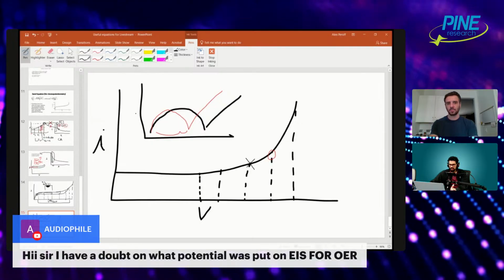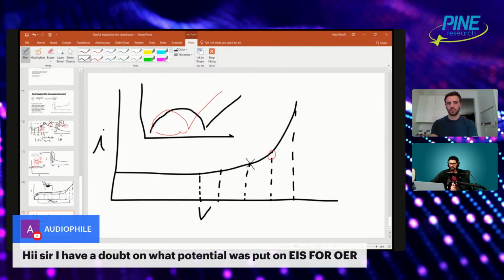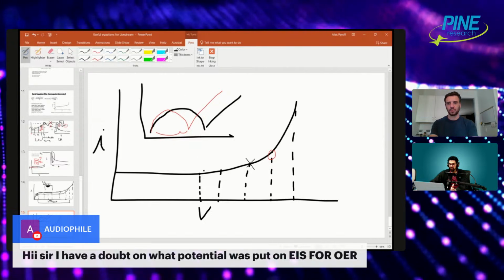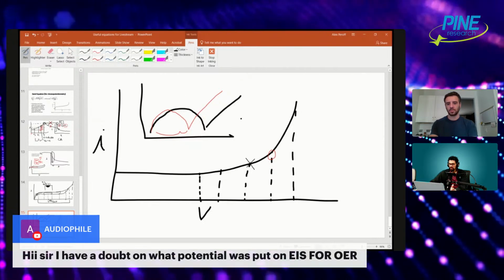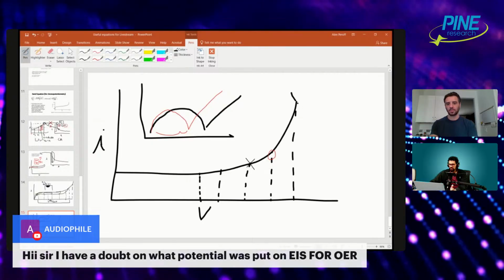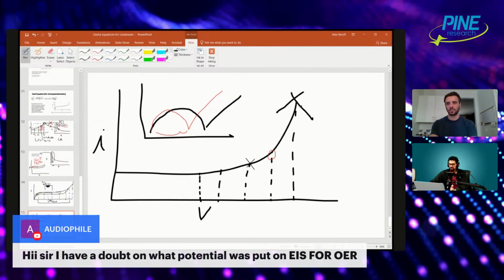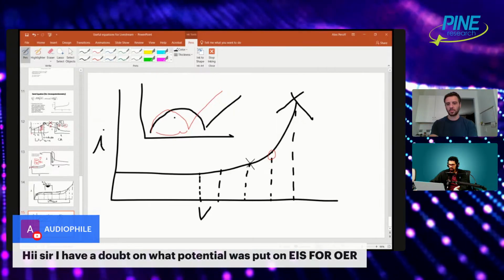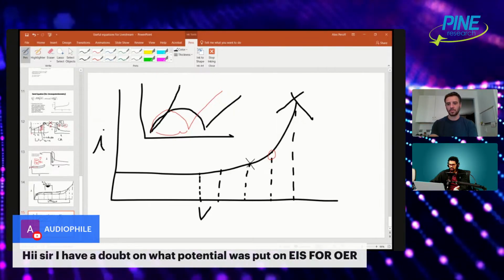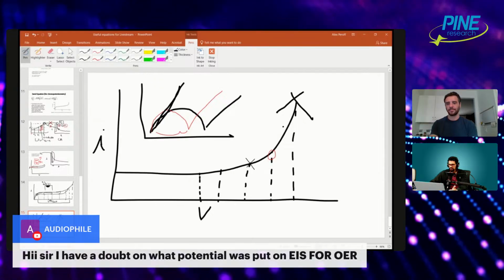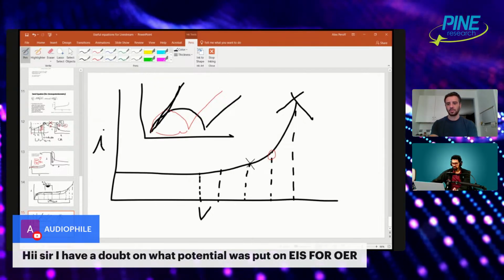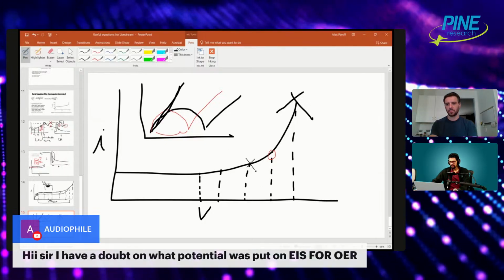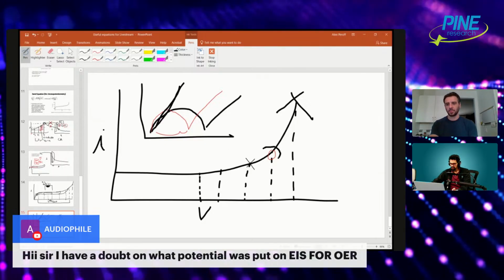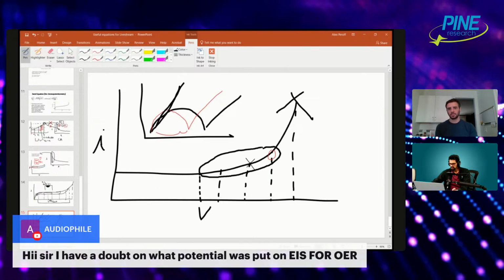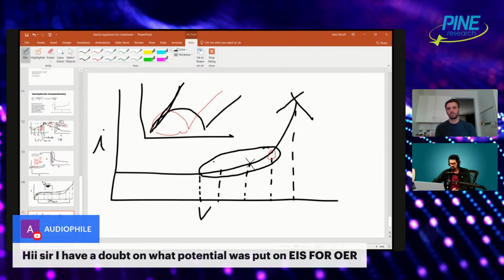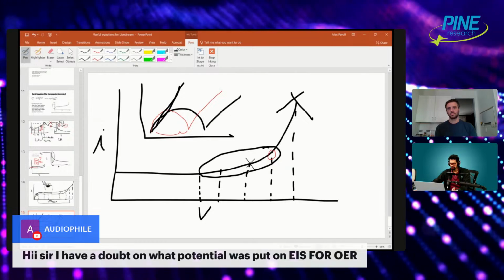So you definitely want to do EIS for OER in a potential range where you're at the onset potential. You probably wouldn't want it up here where there's lots and lots of current, lots of stuff happening. You're probably going to get EIS that looks a little bit like a straight line, as Neil has shown in previous questions. But around this onset, I think you'll learn a lot by actually doing EIS at a few potentials in this range here, where you're near the onset potential.